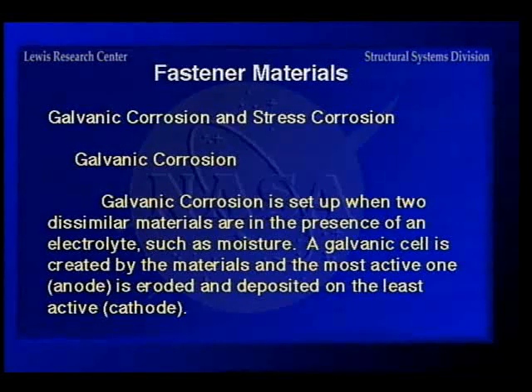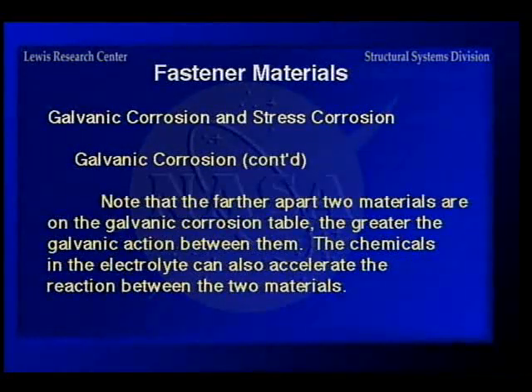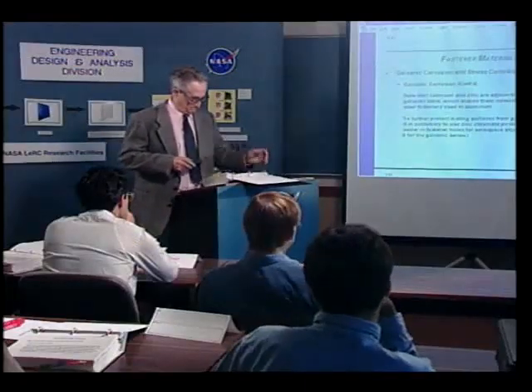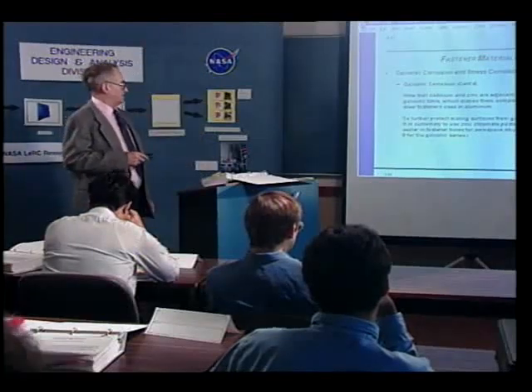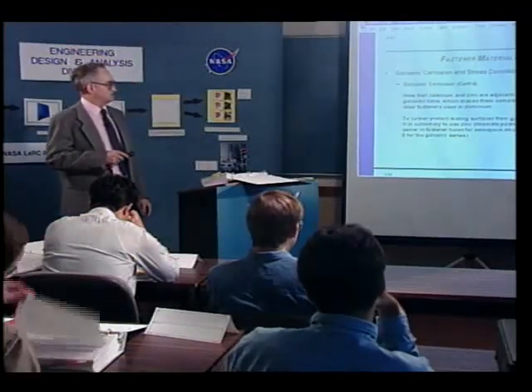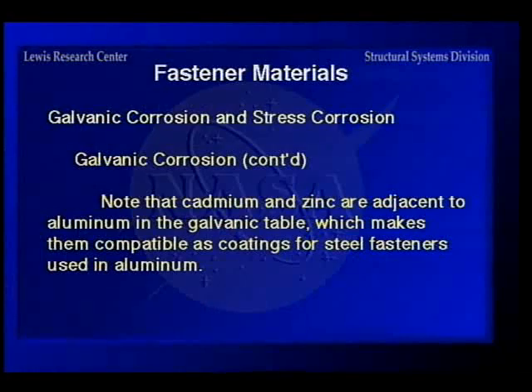And later on, we have a table on the galvanic series that will give you the location in the table of these, and the farther apart they are in the table, the bigger galvanic corrosion cell you develop between the two of them. And of course, cadmium and zinc are adjacent to aluminum in that table, which makes them compatible as coatings for steel fasteners used in aluminum.